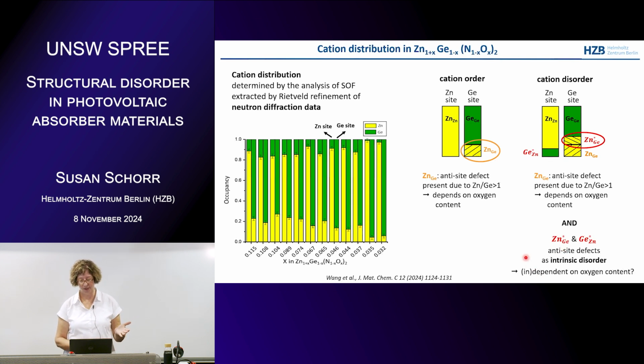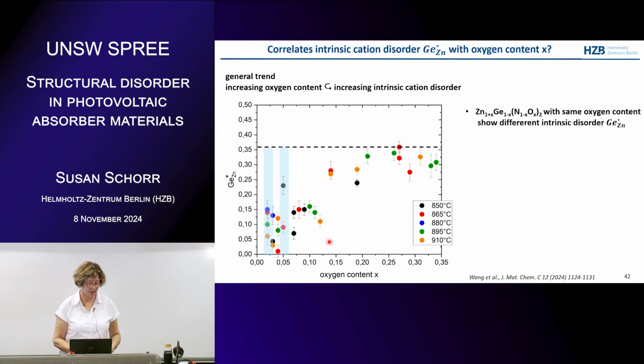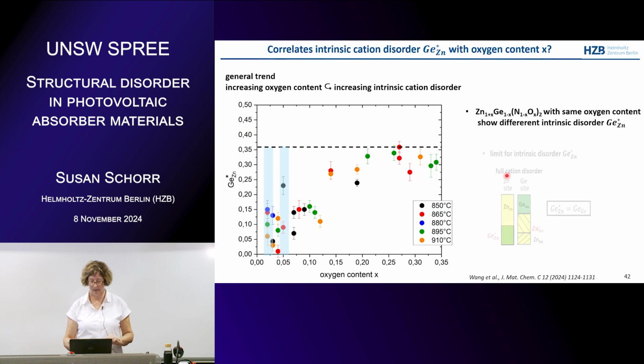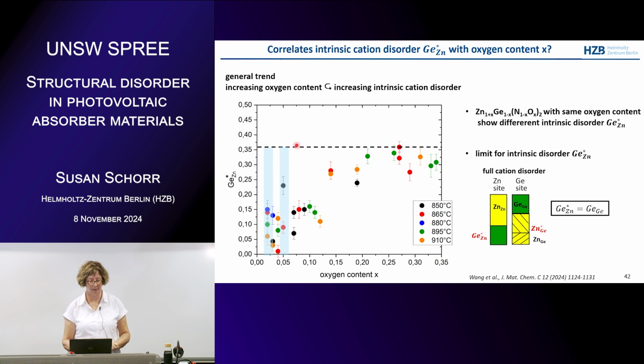And now the question was if this depends on the oxygen content or not. So this is the germanium on zinc star antisite defect and the oxygen content here shown. And you see that, that's why I marked this blue here. Each point is one sample. We have here different samples with almost the same oxygen content, but different amounts of antisites, also shown here. And second, we could say there is somehow a limit for the intrinsic disorder.